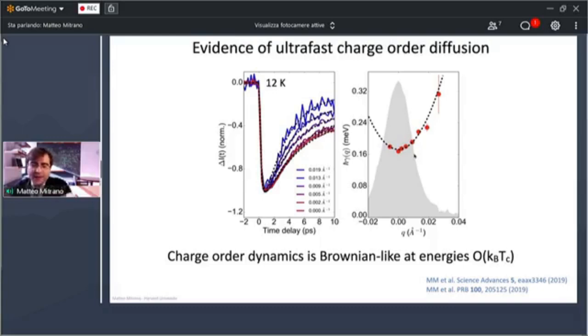So what is happening in this material is that the pump pulse is removing the competing order, and the competing order then reforms through Brownian diffusion and self-organizes again. And this actually sets the time scale for the lifetime of this light-induced state, in which you are removing a competing order that is robbing states at the Fermi level for superconductivity to appear in this material.